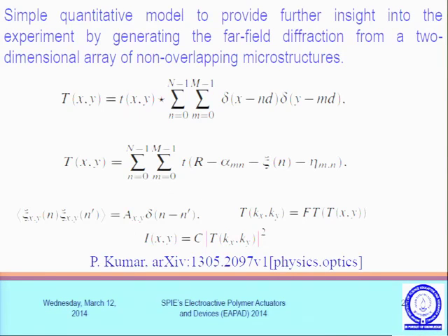So, in order to go into more detail about the forming of the diffraction pattern, we have a simple quantitative model to provide further insight into the experiment by generating a far-field diffraction pattern from a two-dimensional array. What we have done over here, I'm not going into detail on all these things, is create a regular array using MATLAB programming, and we start putting small noise, and correspondingly we measured the diffraction pattern.